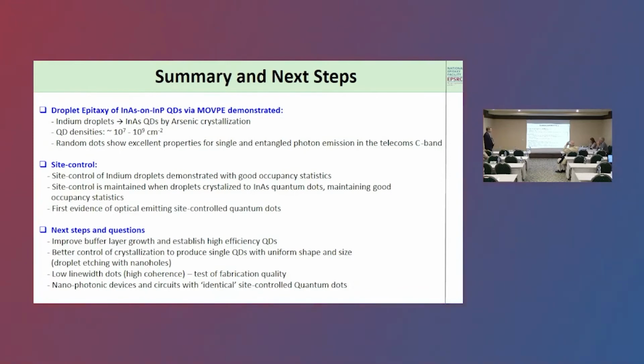So our next steps are to improve the buffer layer growth and establish high efficiency quantum dots and get that optical efficiency up. But we also are looking at better control of the crystallization to produce single quantum dots in the hole, and also control the uniformity of those dots and explore the question of the interaction of the droplet etching with the hole itself, which may help us to control the symmetry of the dot.